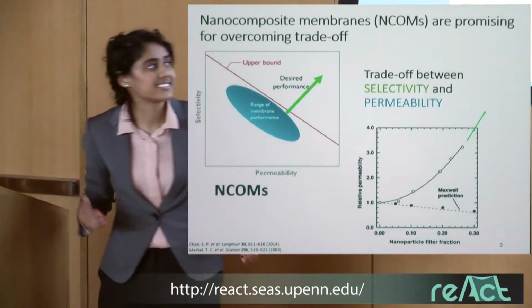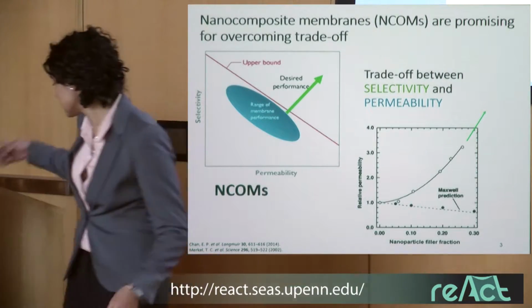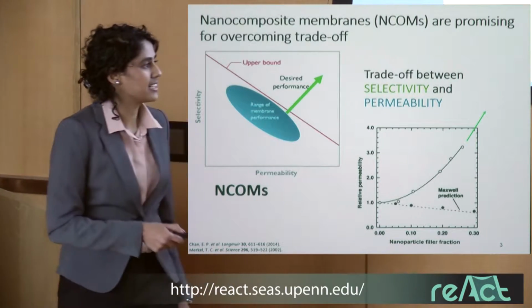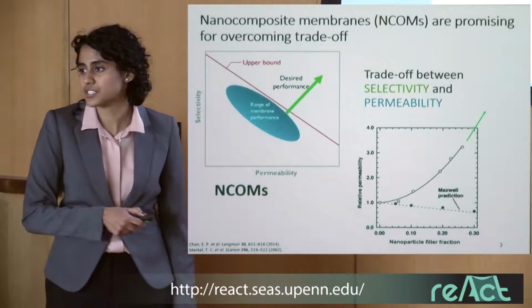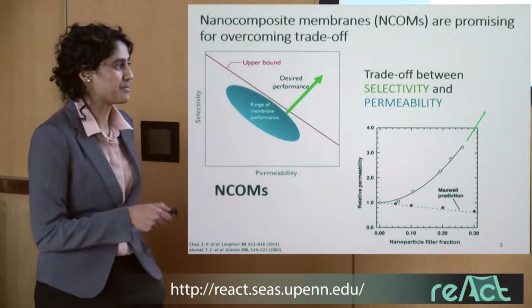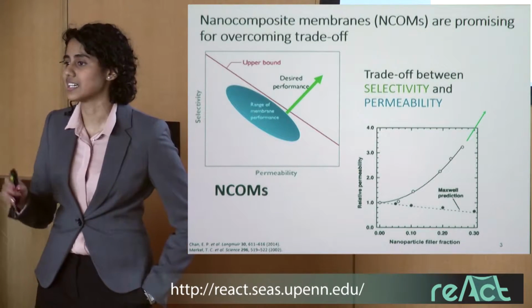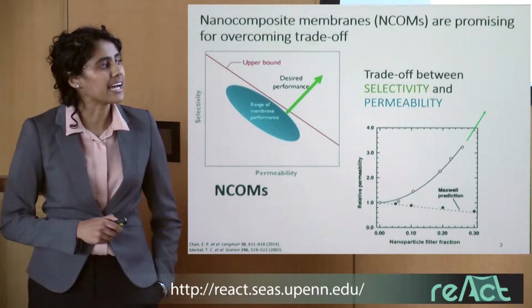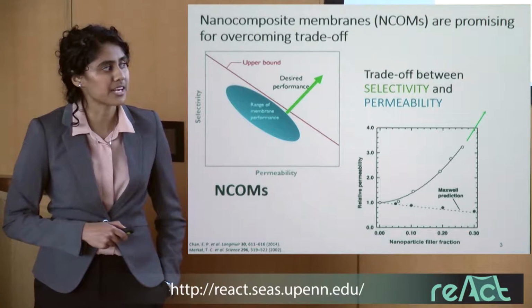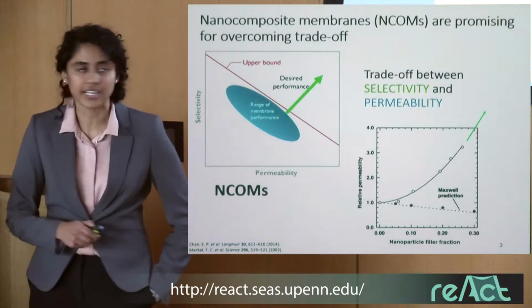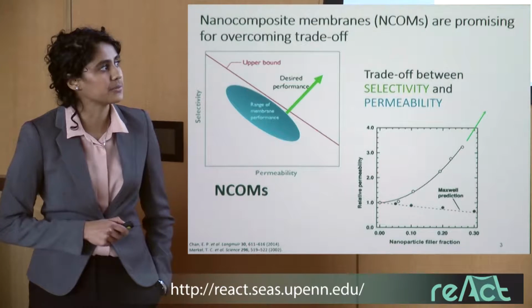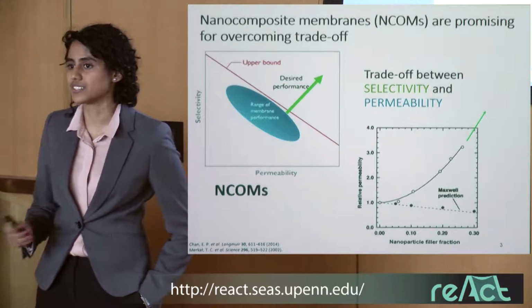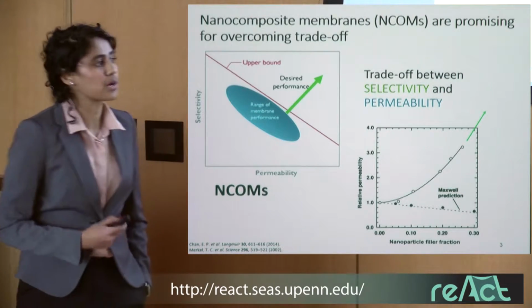So an example is the study that looked at increasing amounts of nanoparticle filler into a polymeric membrane. And what they found is that as they increased how much volume fraction of nanoparticle they had in their membrane, they could drive up the permeability without significantly hindering their selectivity. And this is really promising.